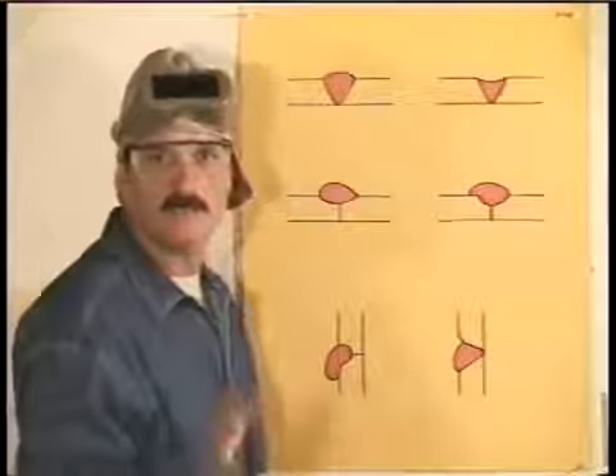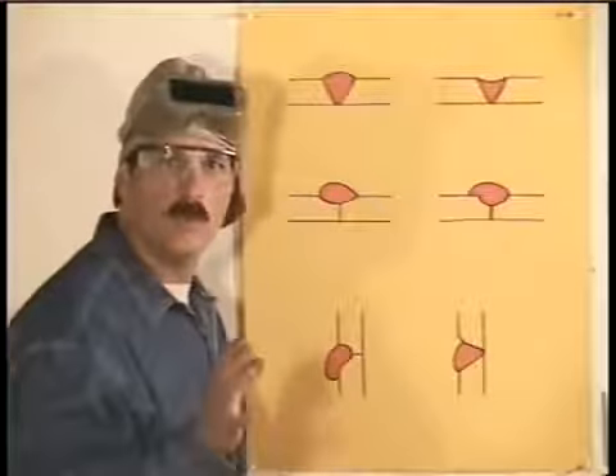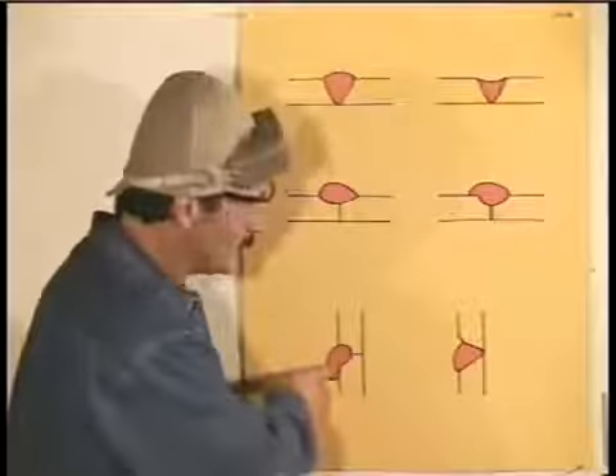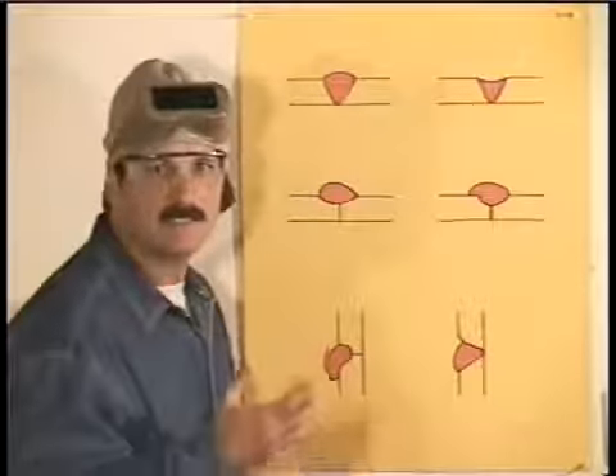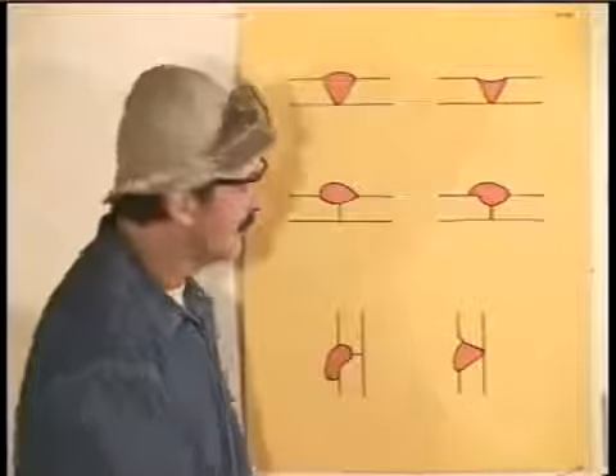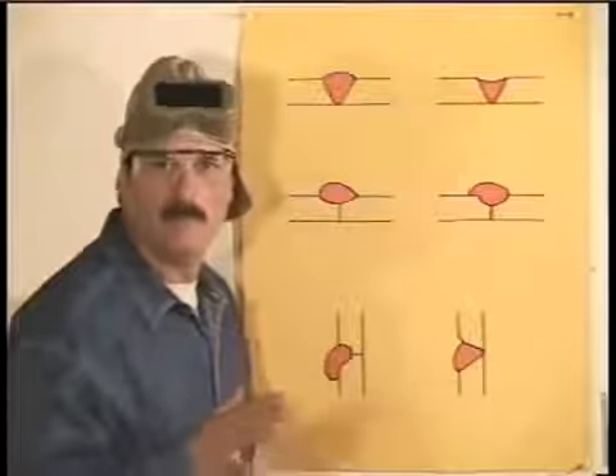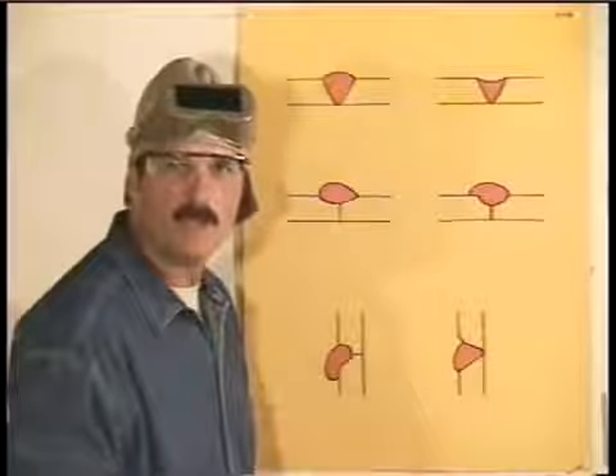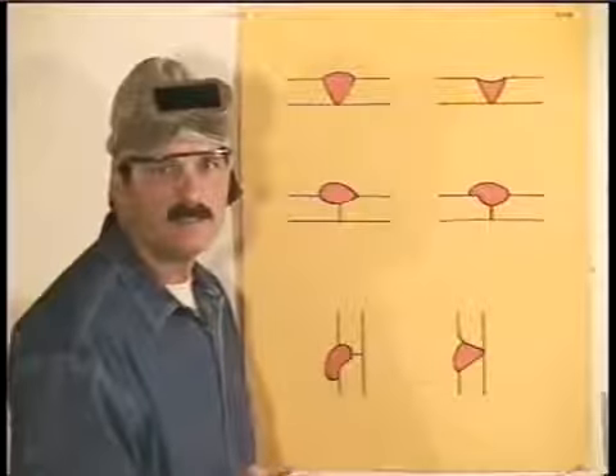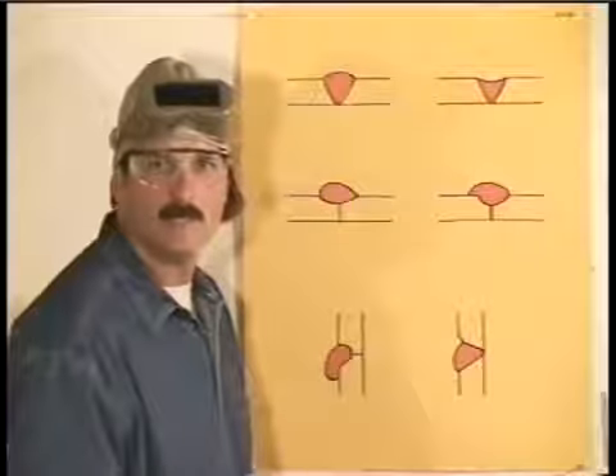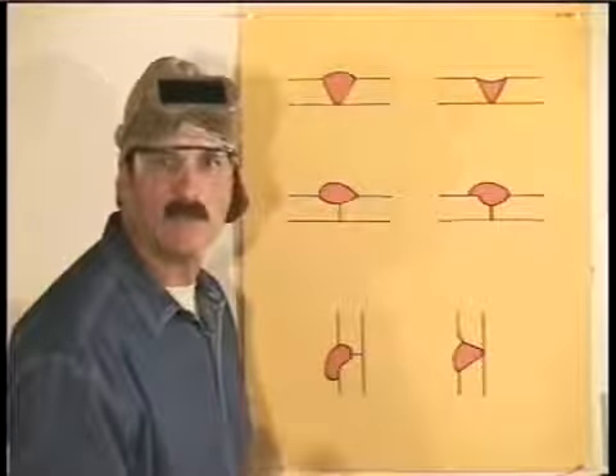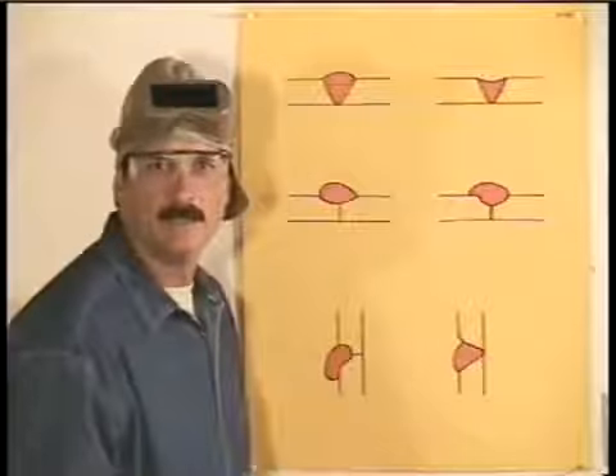On a horizontal, if you try to carry more metal than you can handle, the weld can sag and cold lap the bottom side. Here again, this metal doesn't add any strength to the weld. Undercutting happens when the molten metal follows the heat away from the sides of the weld and you don't put it back. This isn't a big problem in oxyacetylene welding, but it can happen on horizontal welds and horizontal fillets. You always need to watch the sides of the weld puddle and make sure you're leaving enough metal behind. Now, we've been looking at making good weld beads. Let's see if we can use these to put some metal together.